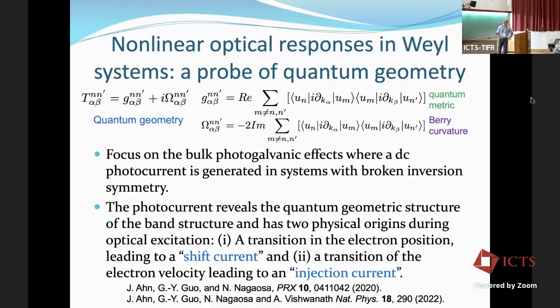So we're going to focus on the bulk photogalvanic effects, which is the situation where we're shining a finite frequency laser on a material. The second order response, where you have two electric fields, one at frequency omega, the other at frequency minus omega, summed together to give you a DC current response in the system, which requires broken inversion symmetry, so the current knows which direction to go. So you shine light on a material, you generate a current, and we're interested in what is the relationship between the current, more specifically the current density that's produced, and the light that we're shining on the system.